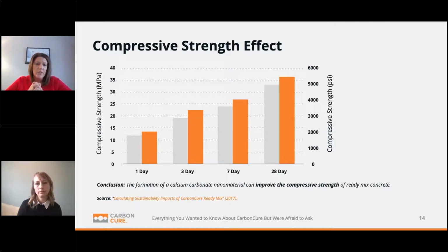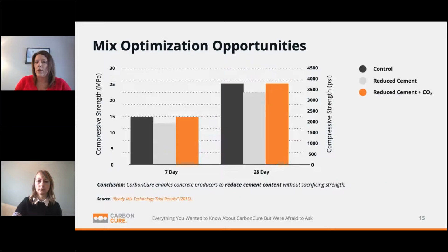So what you're seeing here, if we were to do nothing else other than take CO2 and add it to your concrete mix, that precise dose, we typically see between 3 and 7% improvement to compressive strength at 28 days. Like all things concrete, there's definitely some variability with the results, but we've seen up to 10% improvement just by adding CO2.